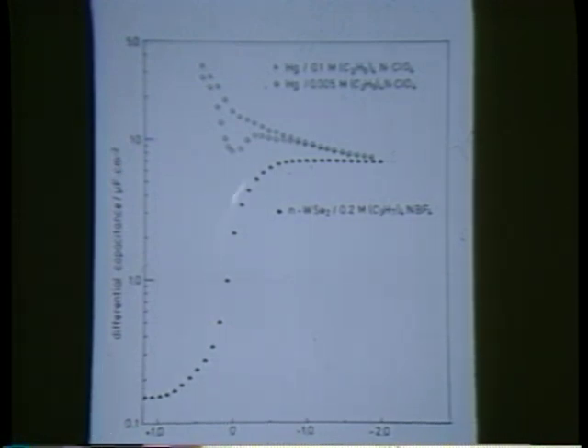I am presenting here measurements with a tungsten selenide electrode, n-type, in now a non-aqueous solvent. The reason that one has to use non-aqueous solvents is just to have a larger range of polarization. And you see here, this is a measured curve, and it follows very ideally what you would expect. This is the depletion range, and here you approach a capacity in the order of 7 microfarads per square centimeter.